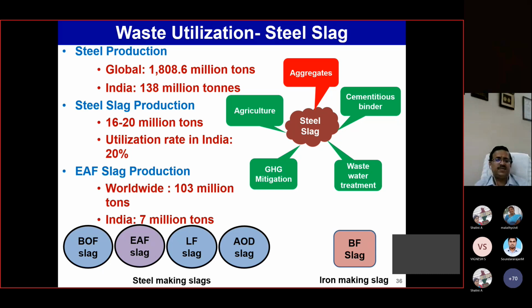Steel slags have different types depending on processing, that is the BOF, also known as Linz-Donawitz or LD slag. BOF means basic oxygen furnace, then EAF slag, electric arc furnace slag. This LF, that is the ladle, is the secondary process. AOD comes from this. If you look at BF, blast furnace slag, it is from iron making, and these are the steel making processes. About 90% or more of BF slag is being utilized in cement production, so that was not a big issue, but the balance here is the steel slag.